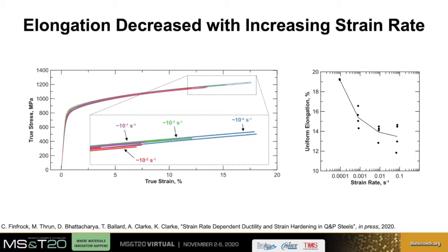From the true stress versus true strain plots, differences in the work hardening rates of various samples are difficult to detect by eye. However, in accordance with the instability criterion, I would suspect that the lowest strain rate specimen generally had the highest work hardening rate at high strains, and thus was able to suppress the formation of a neck for the greatest amount of true strain.